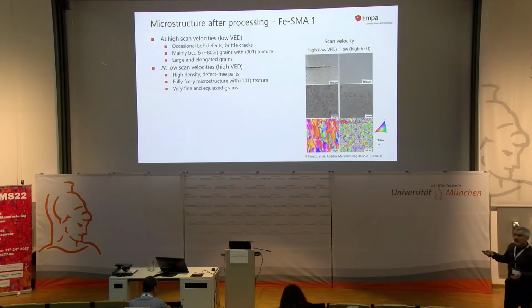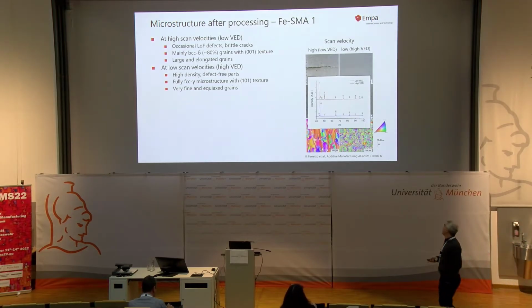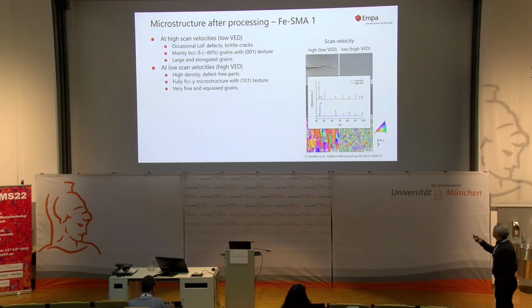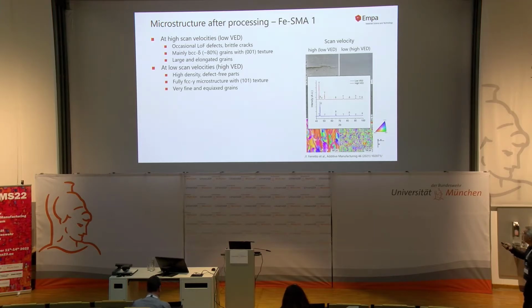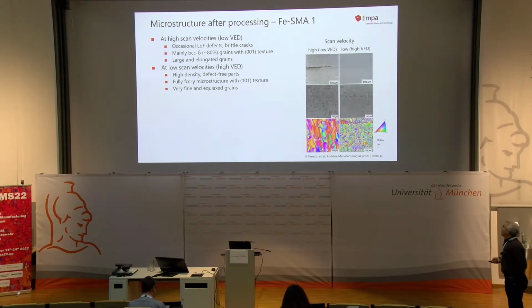If we go to lower scan velocities, so we increase the volumetric energy densities, we could print high density defect-free parts, free of cracks, and we have a fully FCC microstructure with a pronounced 101 texture, and it's very fine and equiaxed grains, which is a bit counterintuitive at first, but if you look into that type of material, it becomes clear. So here again, low VED, we have high amounts of delta. At high VEDs, we have much higher amounts of gamma.